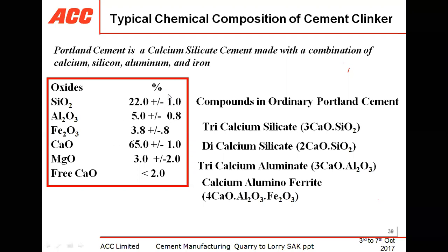The typical clinker, if you carry out the analysis of typical clinker, you will get silica present up to 22%. Then aluminum present up to 5 to 6% in clinker. Then iron oxide Fe2O3 present up to 4%, 3.8% plus minus 0.8%, 3% to 4% के range में generally Fe2O3 present in the clinker. Then calcium oxide present up to 65% in the clinker, and magnesium 3%, and free lime is less than 2%.